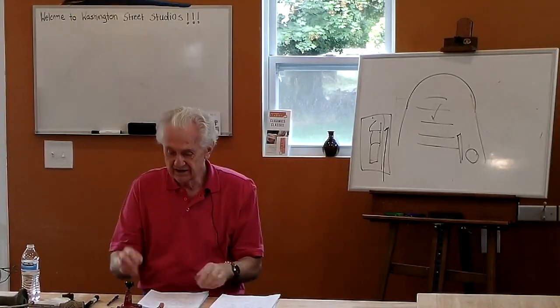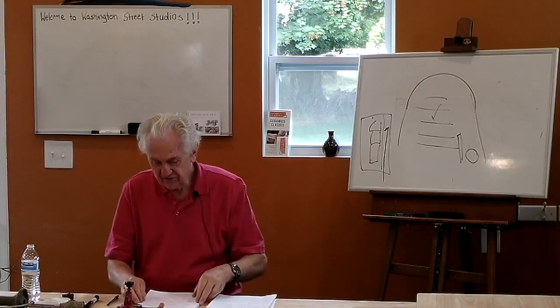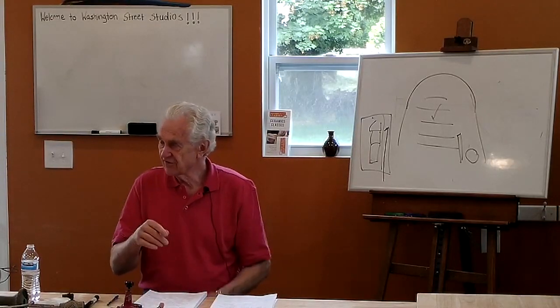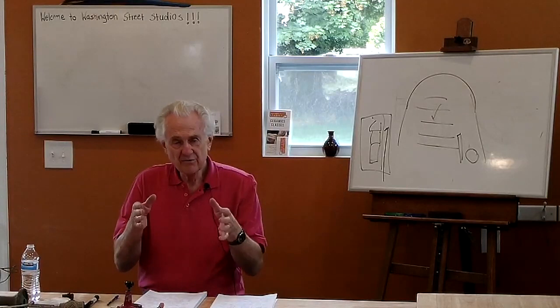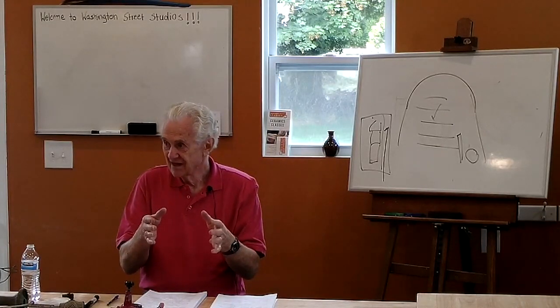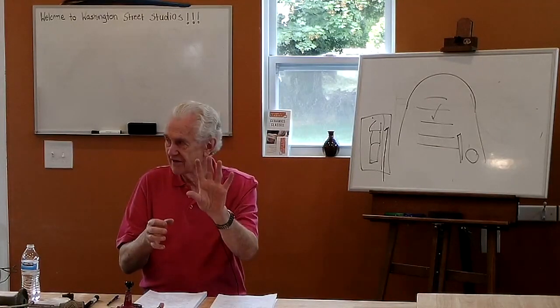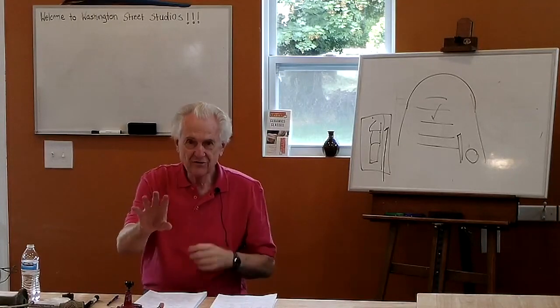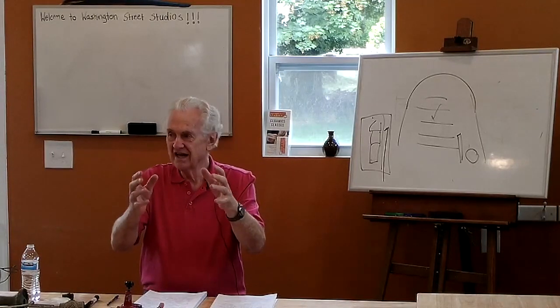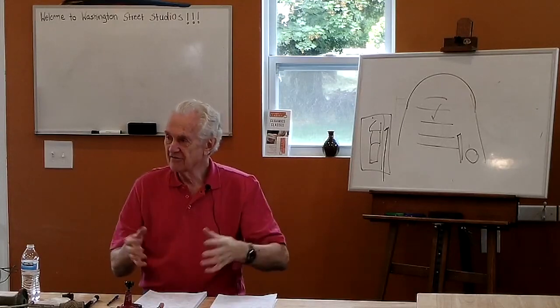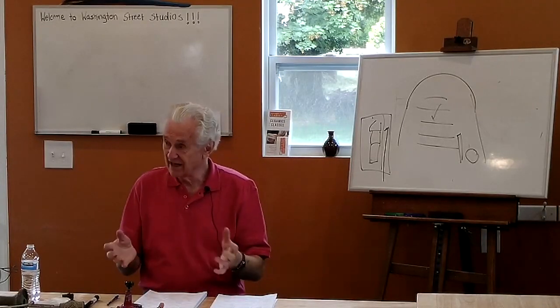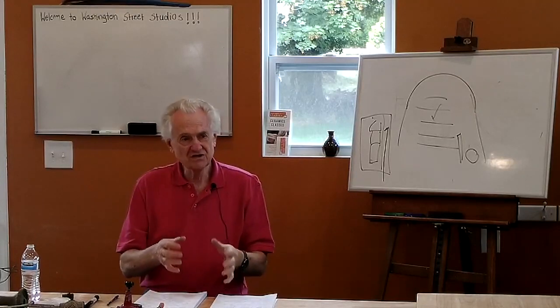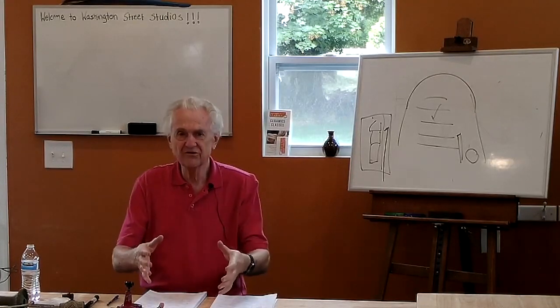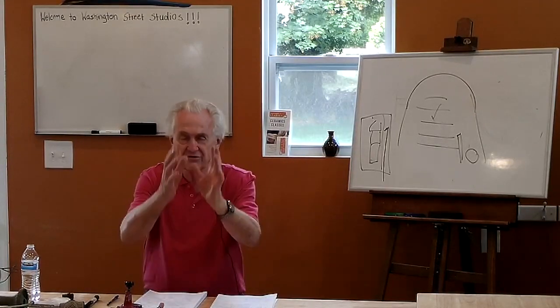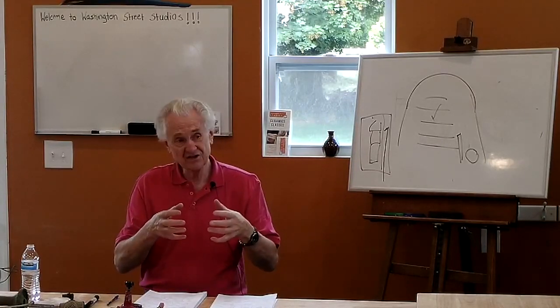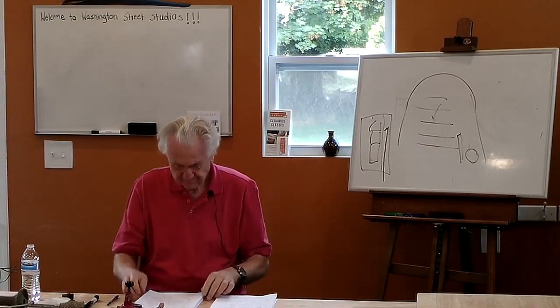Years ago, we had a little kiln at one of the studios where I worked, and the kiln was so small, and the way it was designed was, we were getting the most efficient heating in the chimney. So I had raw gas going through the kiln, some of it was burning, and I had air going through the kiln, and they finally mixed really nicely in the chimney. And so the kiln never quite got hot. The chimney got really hot, but the kiln never would reach temperature, because the most efficient burning wasn't happening in the kiln, it was happening after it got through the kiln, by the time the gases and air had a chance to mix. Why was that?